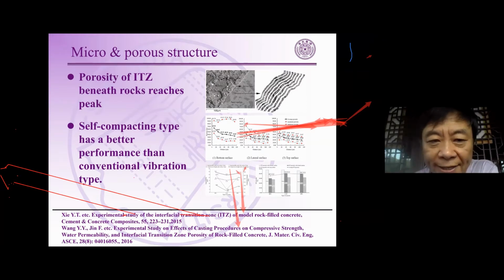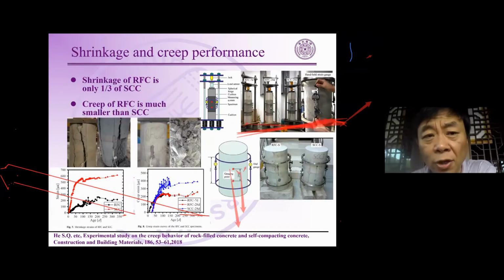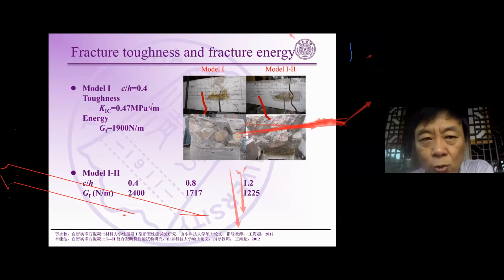We can conclude that the self-compacting type has a better performance than the conventional vibration type. So this study encourages us to build rock-fill concrete dams for very high dams. With this type of concrete we can get very compact performance. And we also tested the shrinkage and the creep. Due to the large proportion of rocks, the rock-fill concrete has smaller shrinkage and creep. And we also studied the fracture toughness of the concrete.